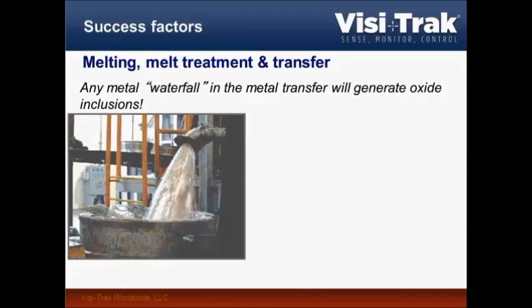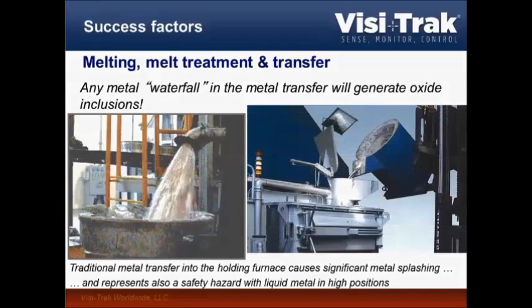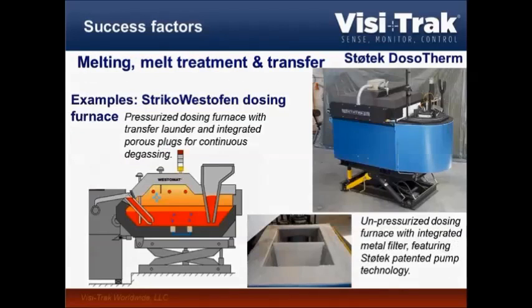Now any waterfall is really bad. Here is a worst case example. So that melt is definitely going to be full of oxide films. But very often I see that even very good die casters do everything right, and they filtered the metal and they degassed and fluxed and cleaned it up, but then they still end up with oxide problems because in the transfer into their dosing furnace, they have to lift the transfer crucible high up, and then you get a 3 feet waterfall coming from the transfer crucible into the dosing furnace. So here again, this can cause problems.